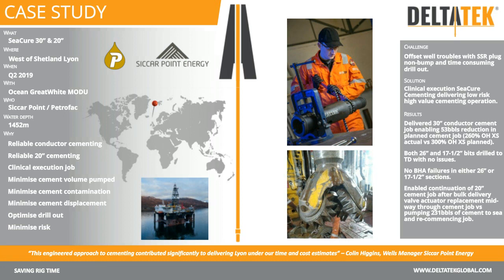Now, this was 231 barrels into the cement job, a 600 meter long 20-inch casing string, which in normal operational scenarios with an SSR plug requires the full casing volume to be pumped prior to the cement going out of the shoe and into the annulus. There was an acceptance by the operator that had they stopped at 231 barrels in, the cement wouldn't have been halfway down the inside of the casing volume at that time. Therefore, shutting down for 45 minutes would have resulted in a detubing and fluid mixing of the front of the cement job. And once the cement job was continued, it would have been an unacceptable risk to continue with the congealed thixotropic cement at the lead. Therefore, the operator concluded that had the plug job been selected in this scenario, 231 barrels of cement would have had to have been circulated to sea and the job would have had to have been recommenced.